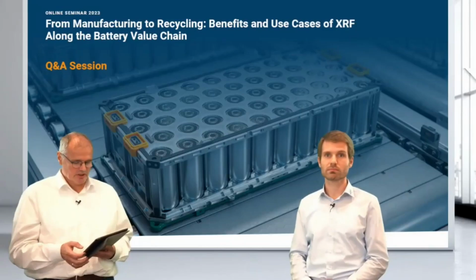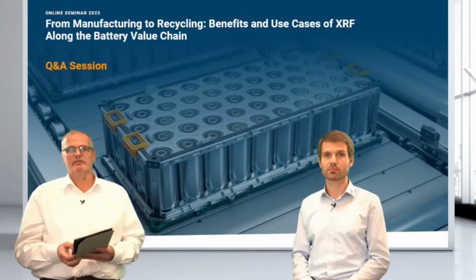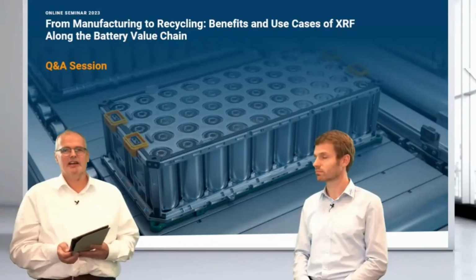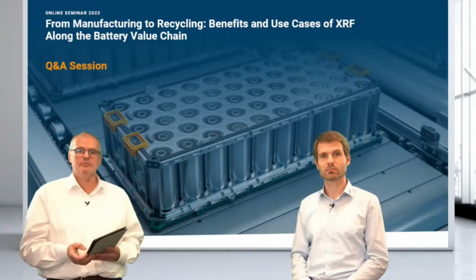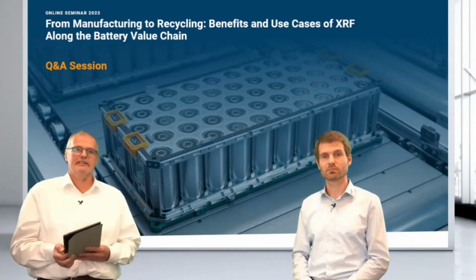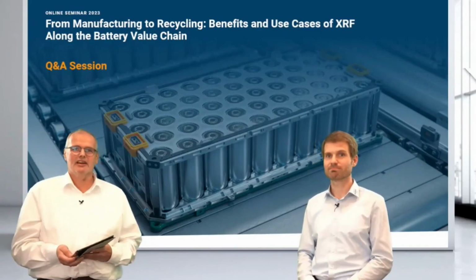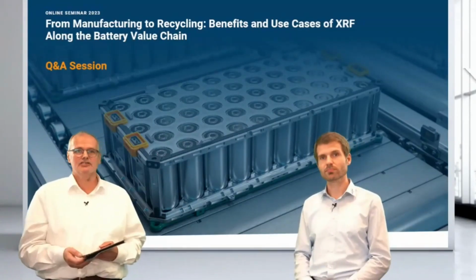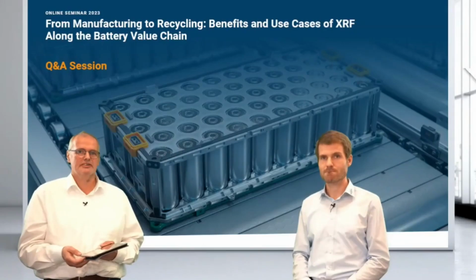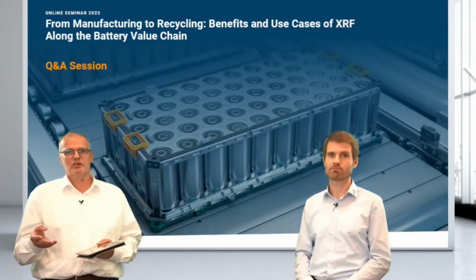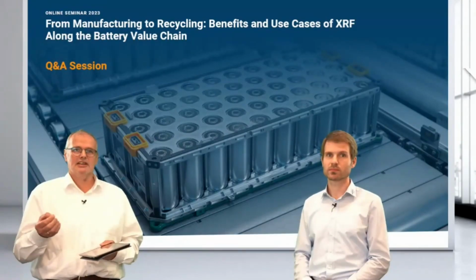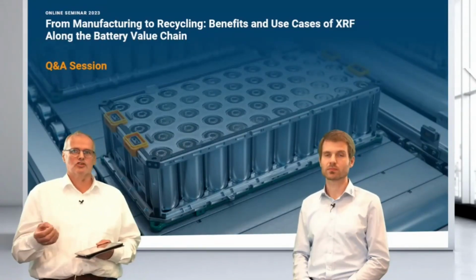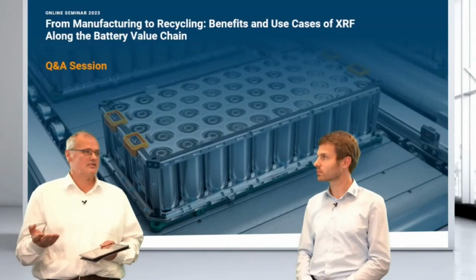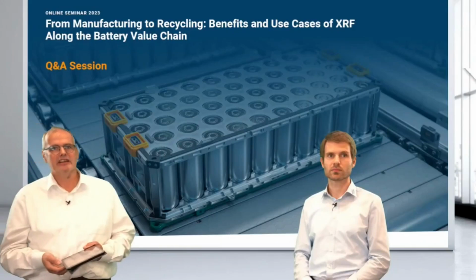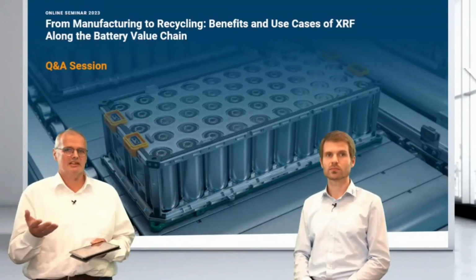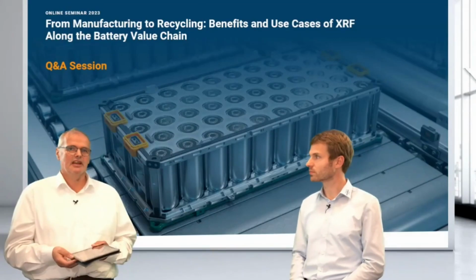There's one question regarding the analysis of lithium, especially in battery applications. Will XRF ever be able to detect lithium? Actually, both wavelength dispersive and energy dispersive technology are not suitable there. The one thing one needs to know is that the X-ray radiation is very weak, so it will be easily absorbed by any material in the way, like the detector foil or the air between the sample and the detector itself.